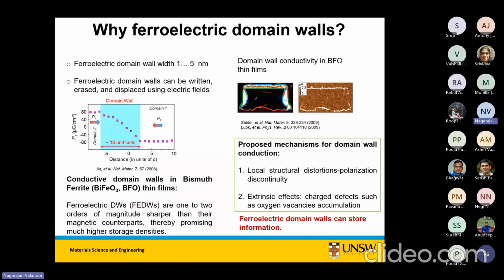Why walls and why not the ferroelectric itself as a memory? Well, the wall itself is quite thin, it's quite small. So if you're really talking about density, you can achieve densities that are quite impossible by just using the ferroelectric portion itself as a bit. Okay, so you have a ferroelectric domain, up or down domain that is separated by a wall. The domain itself can never be stable at that size scales compared to the wall. So the way we push this is that we can get really nice density because the width of the wall is so small.